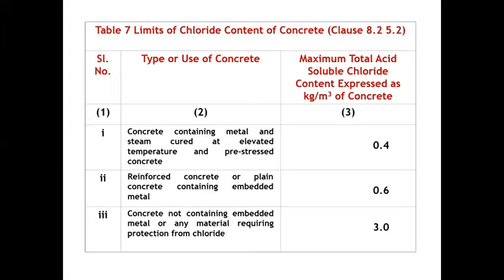If the cover thickness is much lower than what has been specified, then we need to take a call whether we need to go for any protective coating over the cover concrete so that the durability of the structure is extended. Again, you can infer that suppose you have the required cover thickness and good quality, it is not corrosion prone. The required cover thickness is there, but the quality is bad, for example, I do a rebound hammer test, I have the required cover thickness, let's say 40 millimeter is required, 40 millimeter I have, but my rebound hammer value is very low, cover quality is bad. Obviously, it results in corrosion.